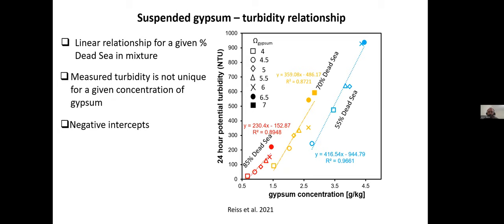Another observation from these experiments, I said when I started talking about the subject, is that the turbidity is used to monitor natural environments. Oftentimes people try to make correlations between the amount of suspended matter and the turbidity, because then you could use turbidity just to monitor and know what's inside your brine. What we see here, when it's an authigenic process, is that even if you have a single chemical component, while there is a linear relationship, each experiment, depending on the crystal size distribution that precipitates and the kinetics, has a different linear relationship. So I don't have a unique relationship between the amount of gypsum and turbidity. And this is something that should be considered when we try to correlate turbidity to the amount of suspended solids or other things that interest us in the water.